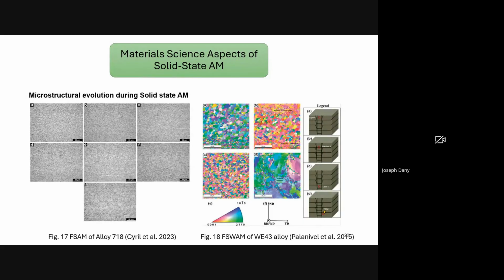Then the third one is thermal gradient and cooling rates. Variation in local cooling rates causes differences in grain size. Faster cooling rates promote finer grain size, while slower cooling due to substrate preheating, thick deposited material or heat accumulation results in coarser grains in some layers. Thermal gradients influence dendritic morphology and phase precipitation as well. And the final one is mechanical deformation differences. The deformation path through the thickness of the deposited layer is not uniform. Edge regions may experience pure shear, while central regions undergo more complex deformation. This leads to subtle heterogeneities in grain size and boundary character between layers or across the build thickness.